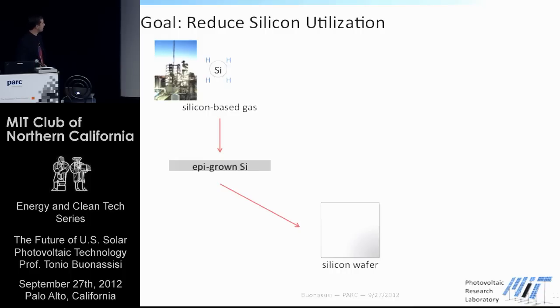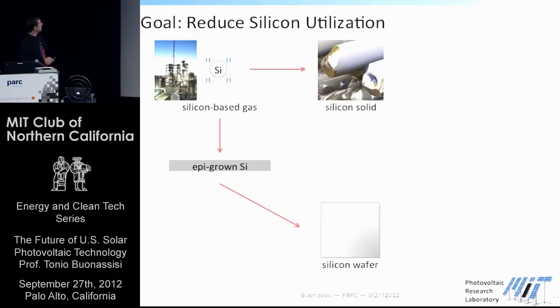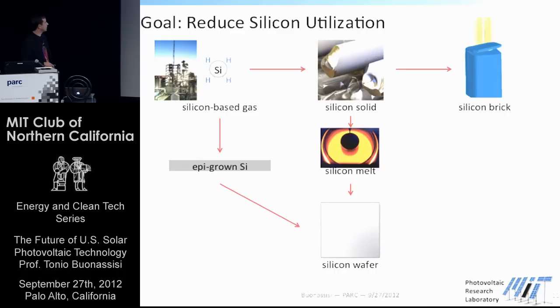So that's one approach. That's usually called the epi approach. There is another approach to go all the way to the solid silicon form, melt it down, and then form the wafer directly from the melt. And there are companies developing this method as well. A third is to go to the brick stage and then use some technique, either ion implantation or straight cleaving using a mechanical lever, to form a variety of cleaved wafers, and then again, you have a wafer. So all of these involve no sawdust. They're all technologies that are called kerfless and have the potential to reduce silicon utilization.